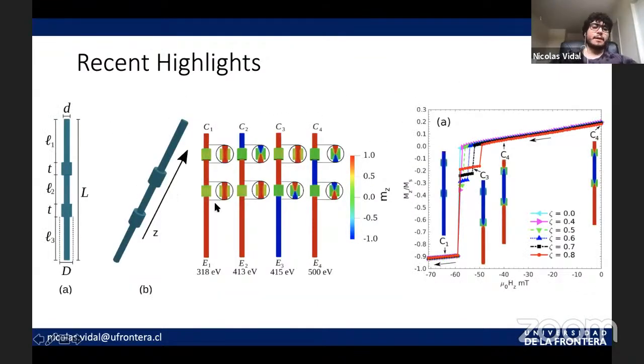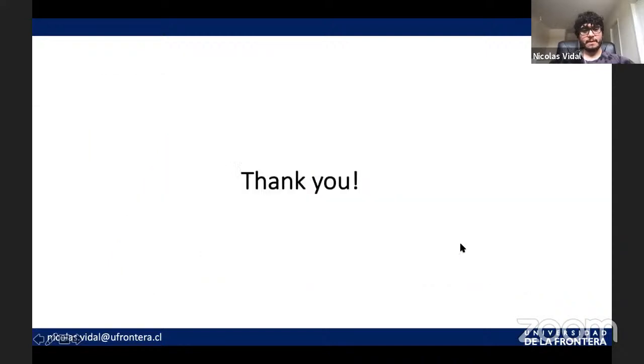And finally, by using micromagnetic simulations in this work, which was published a few weeks ago, by considering this structure we have stabilized different magnetic configurations, and then we proved how robust they are by applying a magnetic field. We found that to destroy such magnetic configurations, we have to reach fields of up to 50 millitesla. So well, that's all I wanted to tell you.